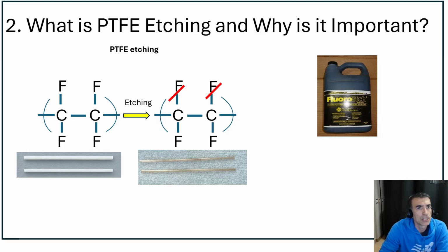What is the PTFE etching and why is it important? As we mentioned, PTFE is very, very inert, and it will not stick to other materials, because of its chemical structure. To make it more reactive and able to adhere to other materials, the first step is to etch the material. Etching is done with a solution of sodium naphthalenide, for example sodium naphthalenide in THF or another solvent. It strips the fluorine groups from the molecular chain. Removing the two fluorine groups leaves behind some transient radicals on carbon atoms, and those radicals are very reactive.